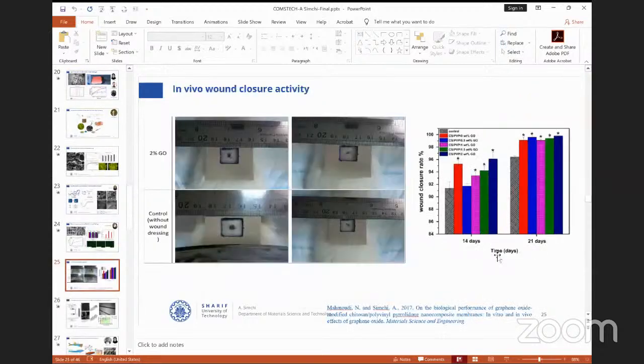Therefore, in continuation of the work, we made more effort with control of the amount of graphene oxide in the matrix, and did a lot of in vivo tests on rats. We have found that after adding 2% graphene oxide, the pad which we made can be used in vivo to regenerate skin after deep injury. As you see in the left-hand side figure, it's a rat with a wound on the surface of the skin, and a mat containing graphene oxide on the surface. And we measured the wound closure, as you see in the right-hand side. We have found that the presence of graphene oxide accelerates the wound healing, which is very wonderful.